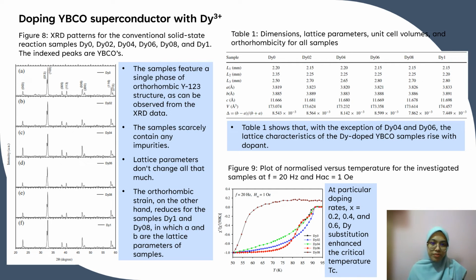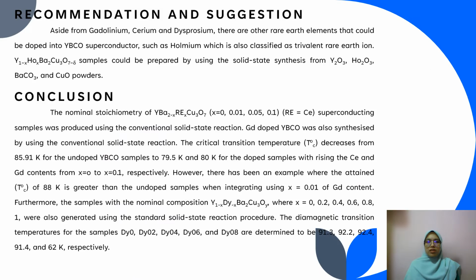rise with the dopant. Figure 9 shows the plot of normalized χ versus temperature for the investigated samples at f equal to 20 Hz and HAC equal to 1 Oe. At particular doping rates x equal to 0.2, 0.4 and 0.6, Dy substitution enhances the critical temperature Tc.